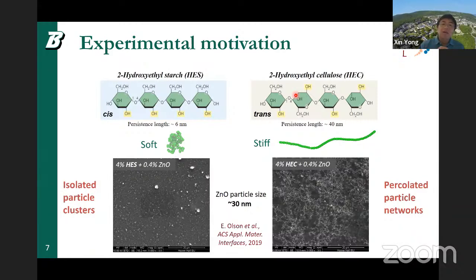and the polymer itself is more stiff. So what's interesting is that they found out that by adding zinc oxide to these two polymers, with basically the same chemical constituent part, the particle structures are completely different. In HES, they observe this zinc oxide basically forms isolated particle clusters, as you can see from this SEM image, while in HEC, these particles assemble into large percolated networks, as you can see here. So you've got these mesostructures.